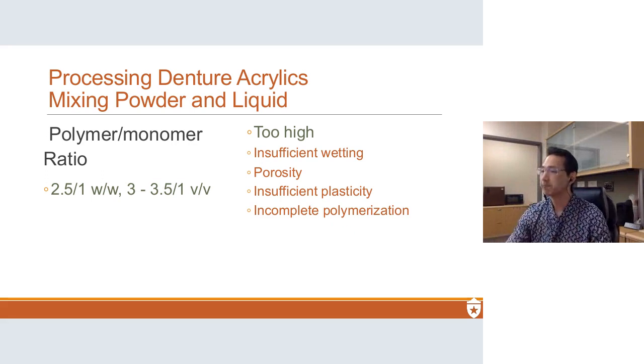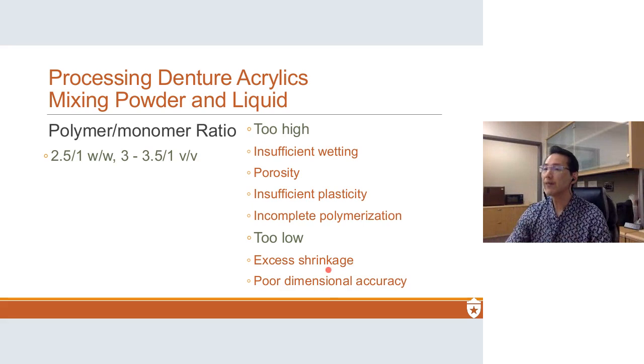Okay, so while all the monomer gets used up and polymerized, that entire mass does not have enough polymer. Okay? Now, if the ratio is too low, okay, not enough powder or too much liquid, then you get excessive shrinkage because the shrinkage, which we will talk more about later, mainly comes from the monomer turning into polymer. Okay? And because of that, you get poor dimensional accuracy.